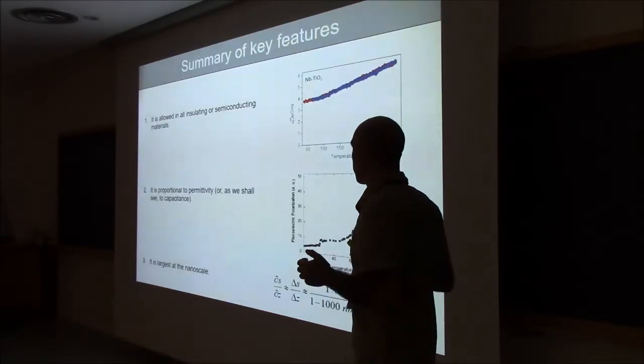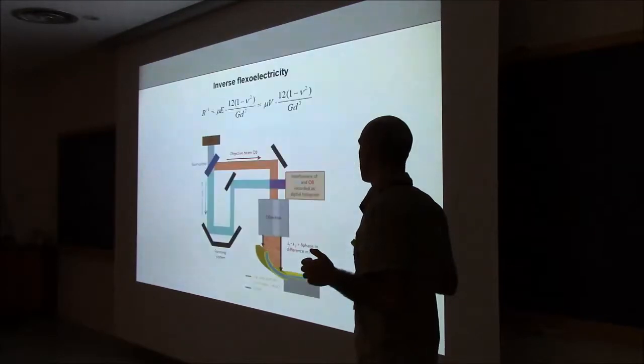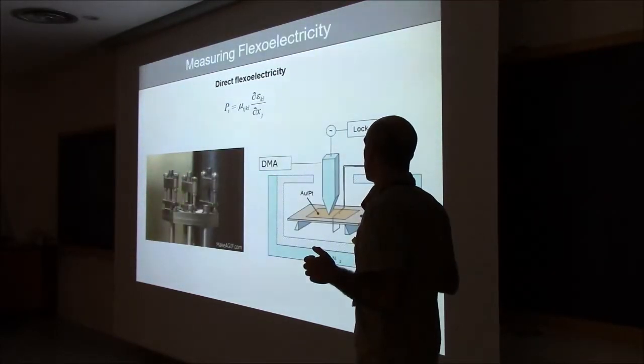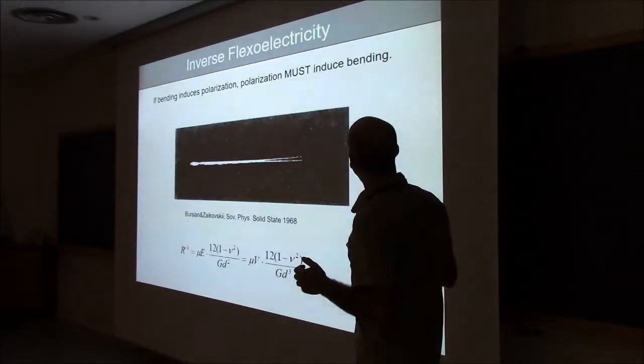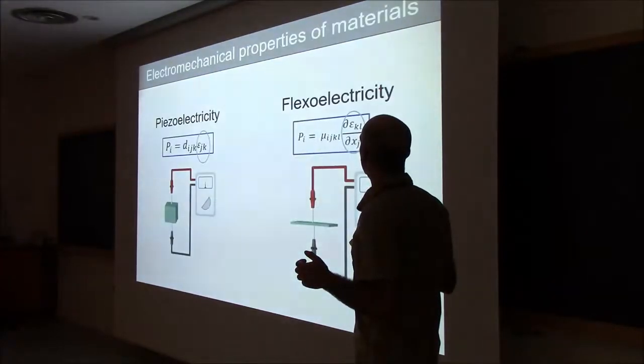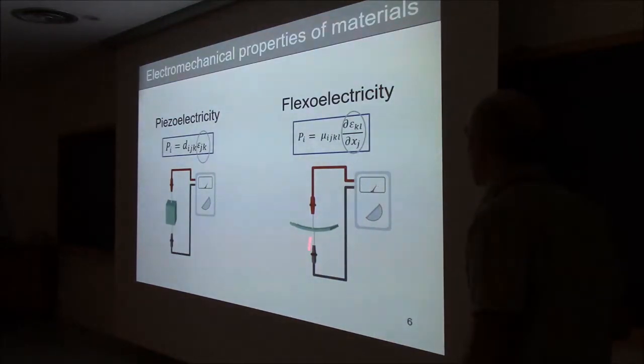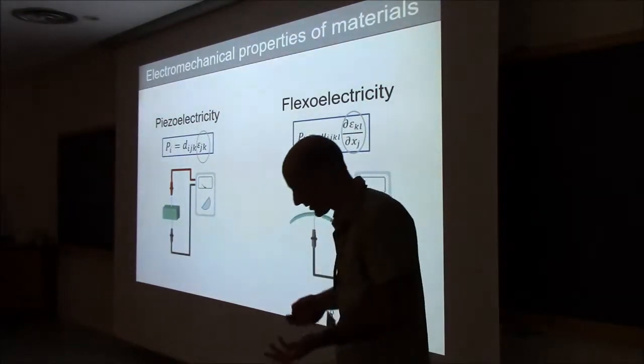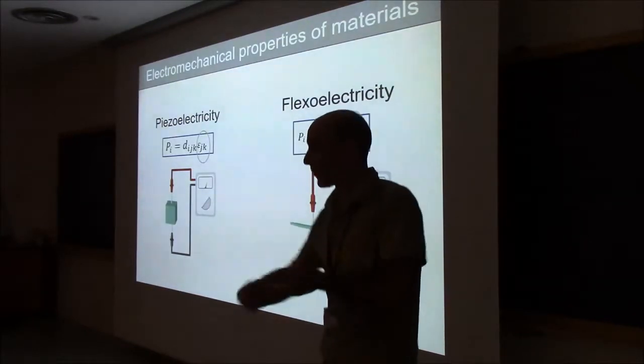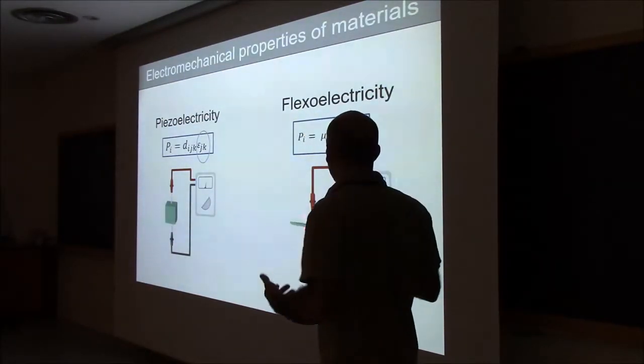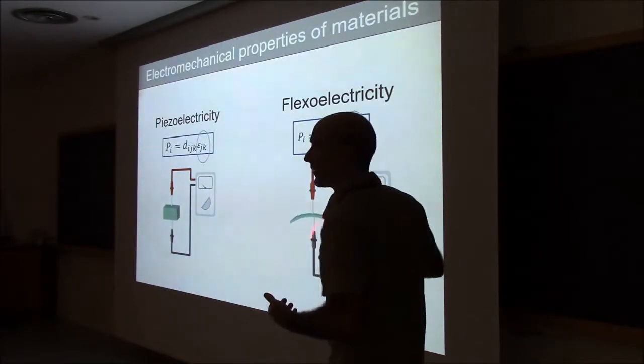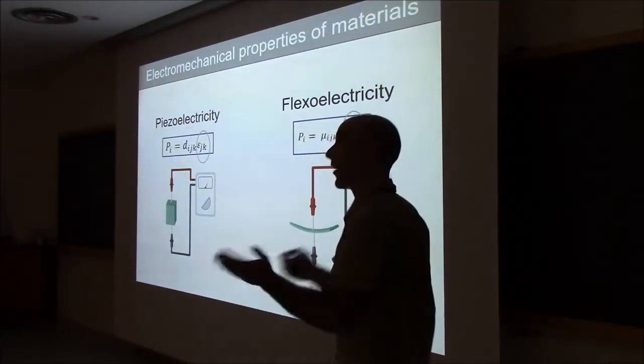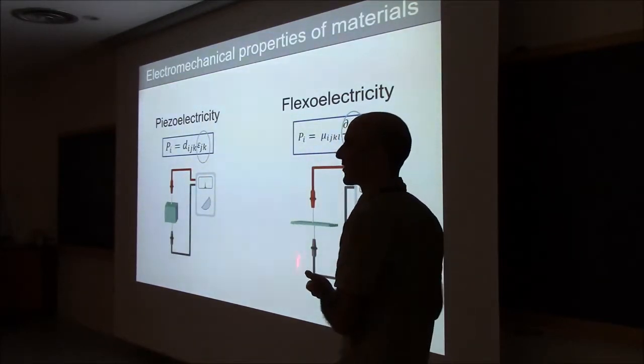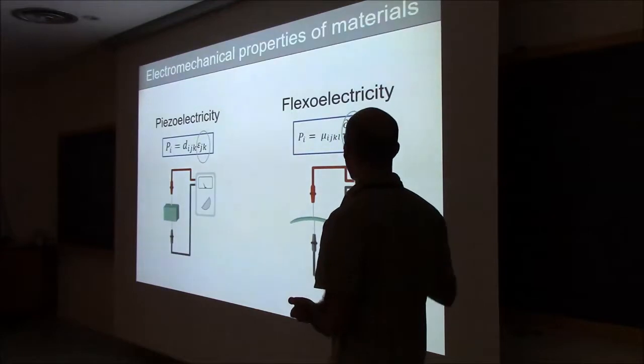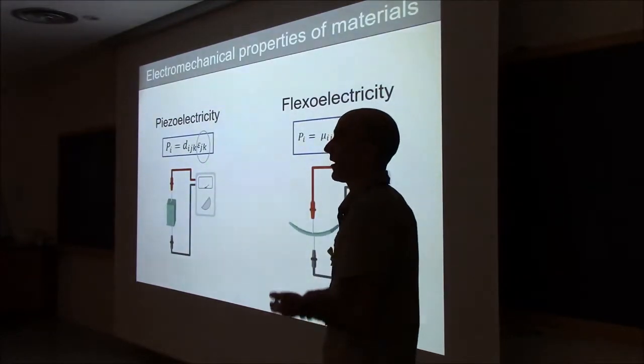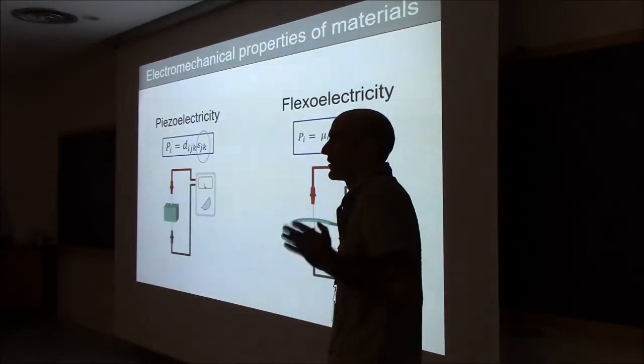Because remember the way in which we measure polarization? Let me see if I can find it. So when I bend this, it will polarize. As it polarizes, you need to compensate that polarization by generating a displacement current that will flow through your ammeter, and that's when you will measure it. However, if your material is metallic, the displacement current is going to flow through the metal rather than through the ammeter. This is a much shorter path than here. So maybe I am polarizing my material, but I just can't measure it.